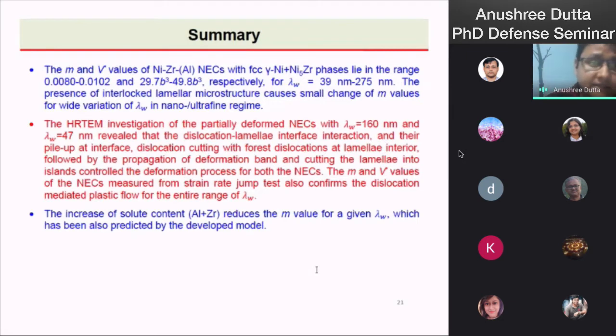The summary of this chapter is strain rate sensitivity and activation volume of these NECs lie in the range of 0.008 to 0.0102, whereas activation volume is 29.7 to 49.8 b cubed. The presence of interlocked lamellar microstructure causes small change of m as compared to the other polycrystalline alloys.